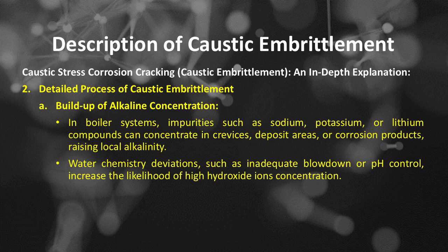Number A, buildup of alkaline concentration. In boiler systems, impurities such as sodium, potassium, or lithium compounds can concentrate in crevices, deposit areas, or corrosion products, raising local alkalinity. Water chemistry deviations, such as inadequate blowdown or pH control, increase the likelihood of high hydroxide ions concentration.